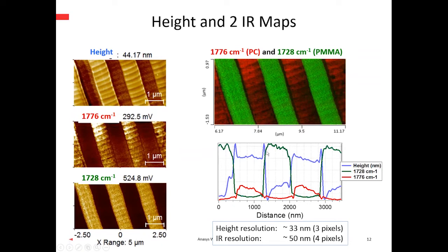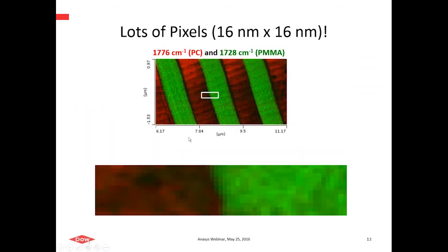And then we can look at this fall off of the edge either in the vertical height change or the spectral change for each of these resonances, we can estimate resolution at like 80% cutoff along that edge. And if we do that, we find that the IR spectral spatial resolution is about 50 nanometers, or in this case, it's about 4 pixels. So clearly, we're well below the 100 nanometers we anticipated.